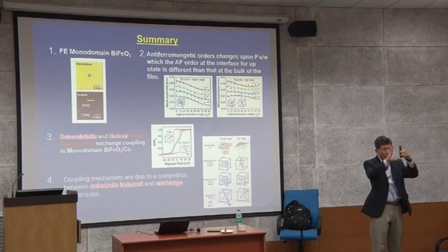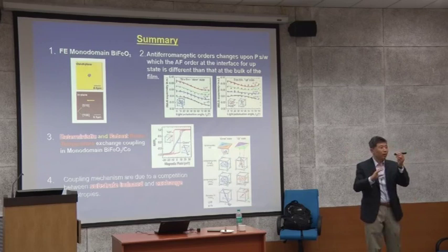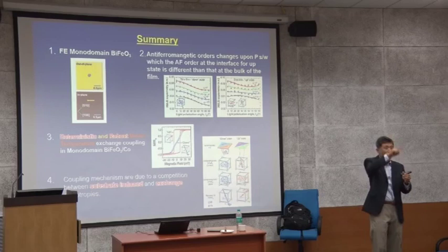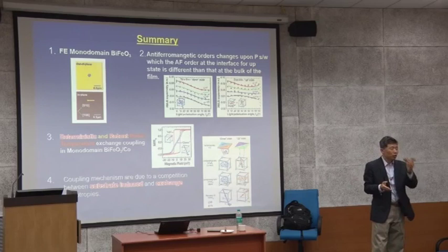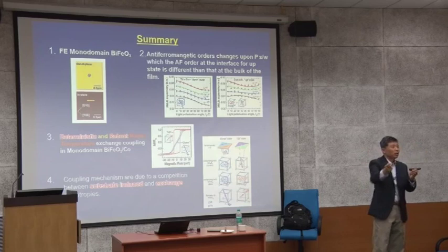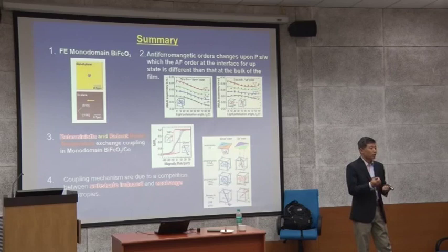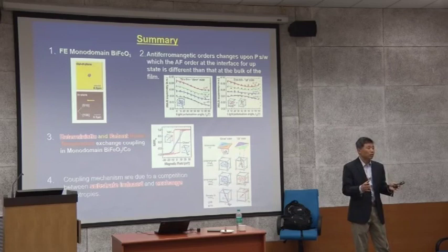One comes from the longer lattice parameter, which is at a smaller angle. The A domain has the shorter axes, A and B, so that angle comes later. So your peak is a double peak, and you know this one is multi-domain. Then this one is aligned this way, that one aligned that way, you have those two, and you measure an off-axis 101 phi scan. In the phi scan, you only see two peaks every 180 degrees if everything is aligned one way. But if you have both, every 90 degrees you get this one and you get that one. So you can see all the domain structures without a ferroelectric measurement, just an X-ray measurement, because that's coupled with the structural domain, with the structural distortion.